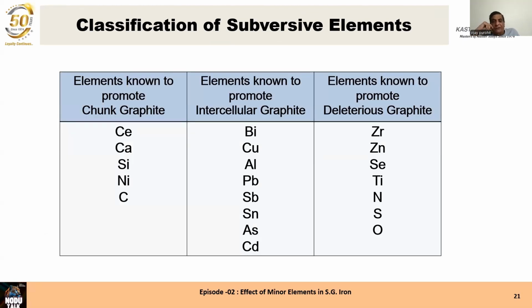This is a list of subversive elements which are known to promote chunky graphite on the left-hand side: cerium, calcium, silicon, nickel, and carbon. The elements which are known to promote intercellular graphite, that means the graphite in between the nodules, mostly flake graphite or different shapes of flake graphite, are bismuth, copper, aluminum, lead, antimony, tin, arsenic, cadmium. These normally come from non-ferrous scrap pieces that may enter into the charge mix used for melting S.G. iron base metal.